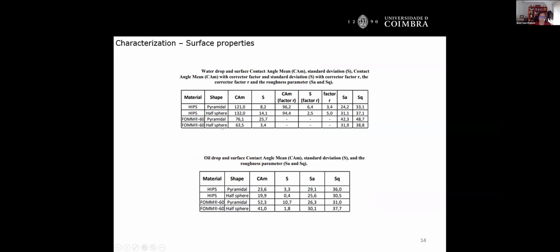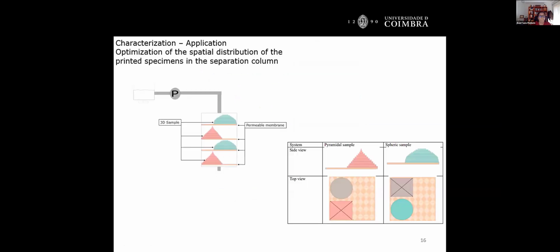We made the same thing for water and oil, for HIPS, for both shapes, and the contact angles after correction with the roughness, okay? And then we have also the values of the surface roughness, just to confirm that, of course, we had a very high value of surface roughness. In order to characterize, we first made preliminary studies where, through those meshes, those membranes that we have to put in the column, we saw what was the best one in order to let the liquid flow.